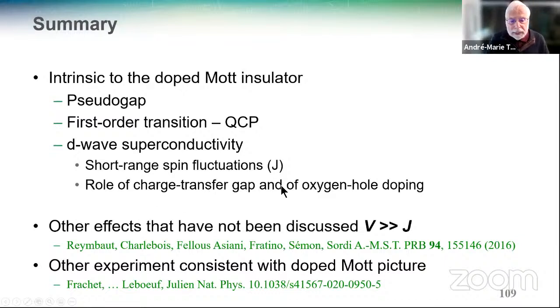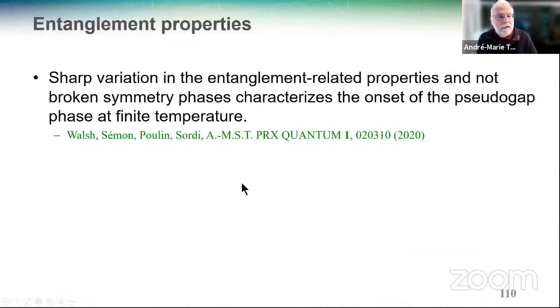And I showed you that we understand almost quantitatively the role of the charge transfer gap and the oxygen-hole doping. There are other objections that you could have, such as the fact that we neglected nearest neighbor Coulomb repulsion, but in fact we have some papers that look at that and show that it's no problem. There are recent experiments that are consistent with the doped Mott insulator picture. I was supposed to talk about entanglement properties, but I won't since it's very late. The upshot is that sharp variation of entanglement-related properties, and not broken symmetry phases, characterize the onset of the pseudogap at finite temperature.